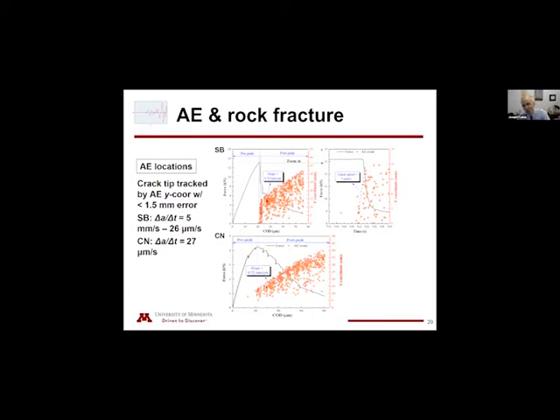So this slope, and of course, there should be some nonlinear behavior that is taking place as the crack increases, but it's more or less well fitted by this line, and that gives us a crack velocity of 26, and for the center notch a little faster. And I would say the locations are tracking the fracture. This is the rapid propagation, and this is where we get the 5 millimeters per second of crack velocity.